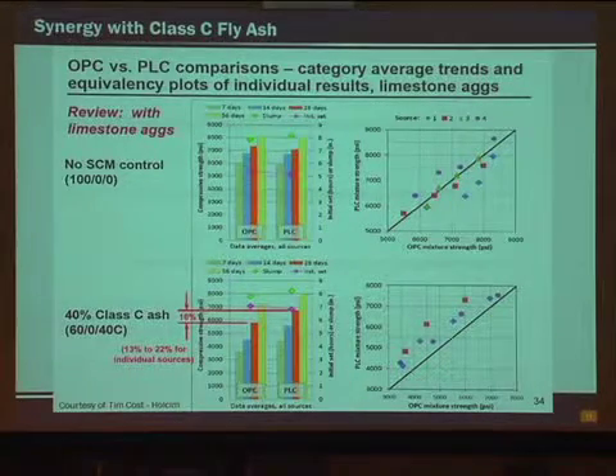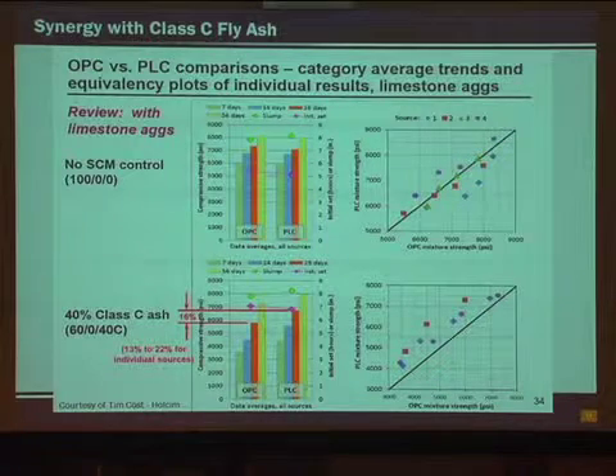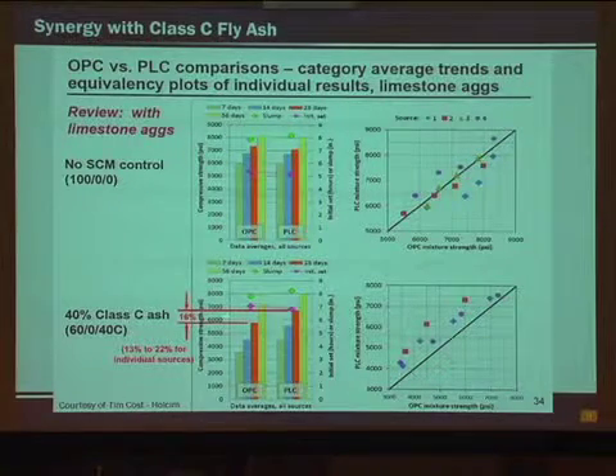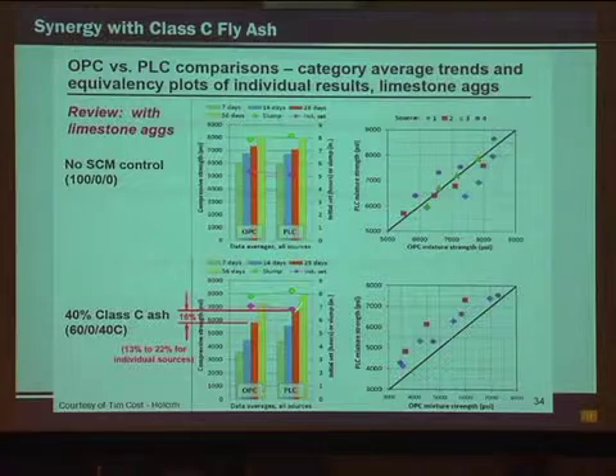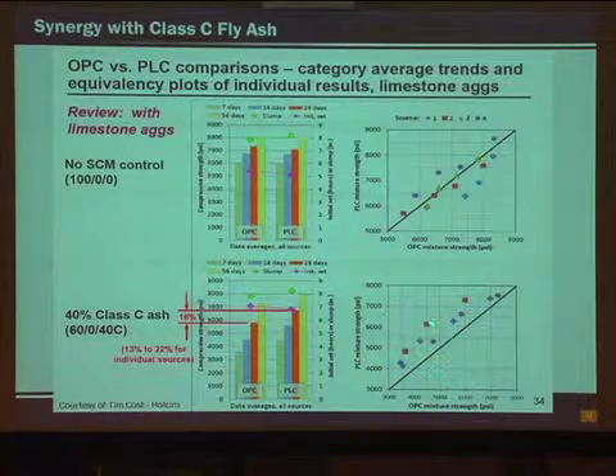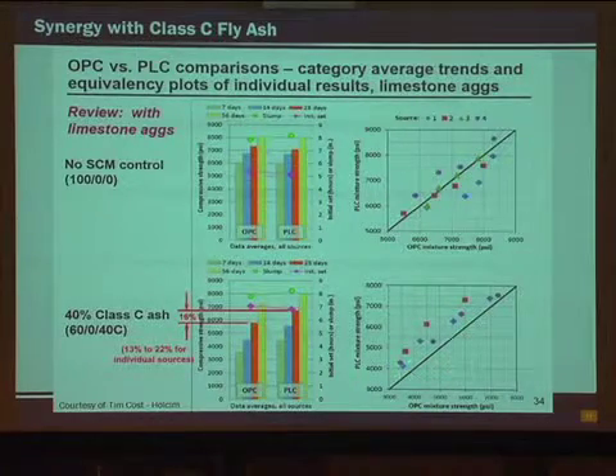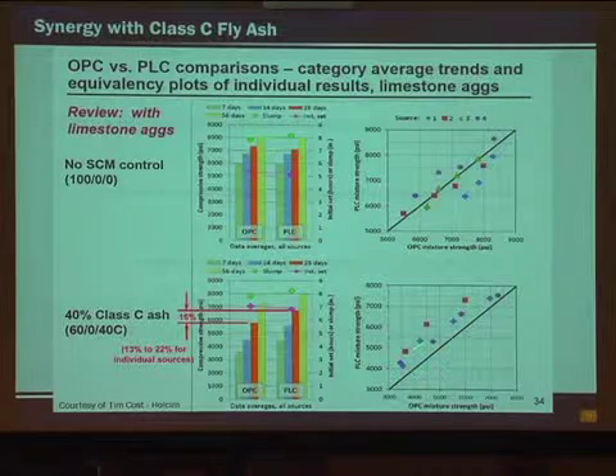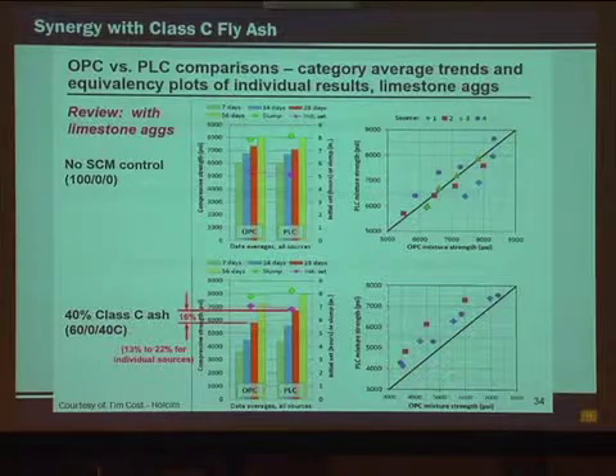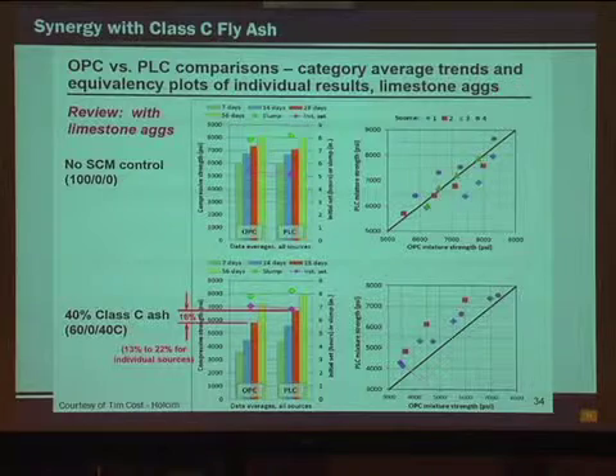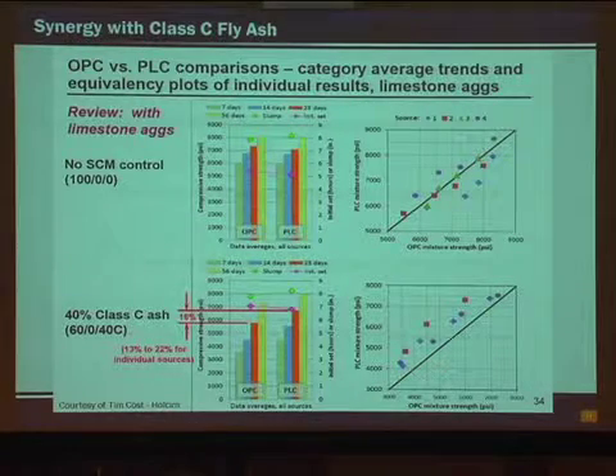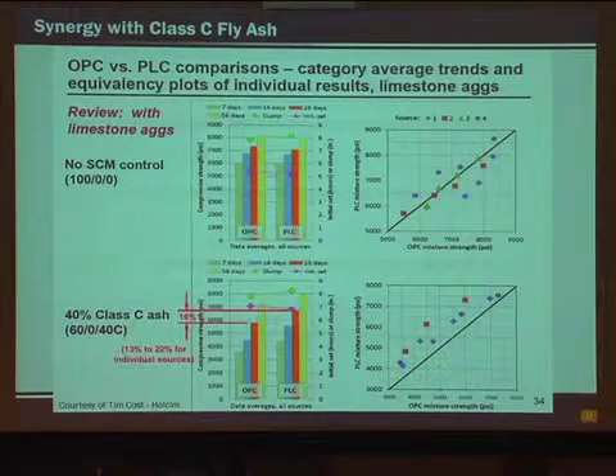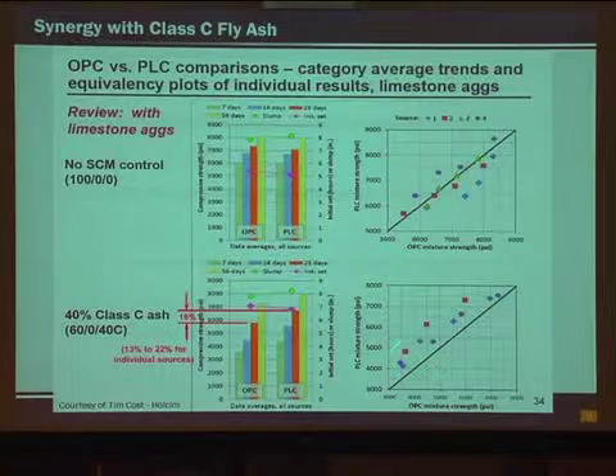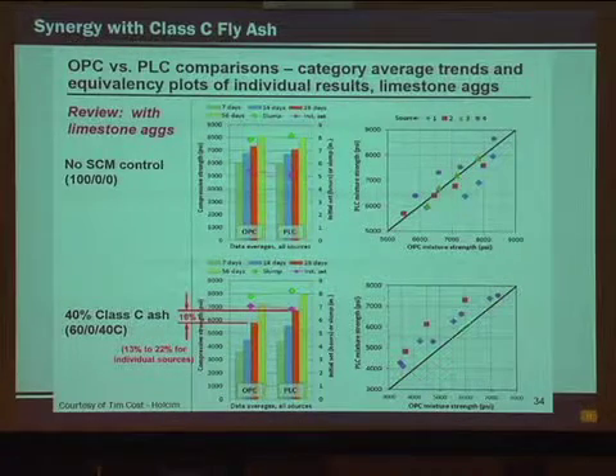Now we go and we add 40% of the Class C fly ash. And now we see a 16% increase in strength at 28 days. And again, on the 1-to-1 plot, all our strengths are now above the 1-to-1, showing that when you add the Class C fly ash to 1L cements, we're starting to see this synergy of increased strength right here.